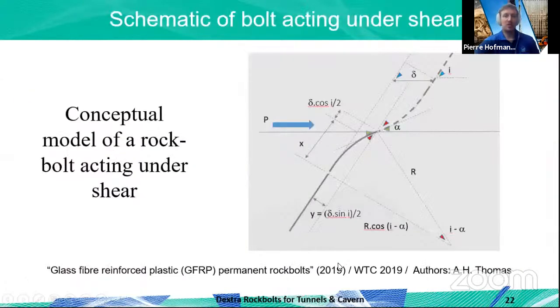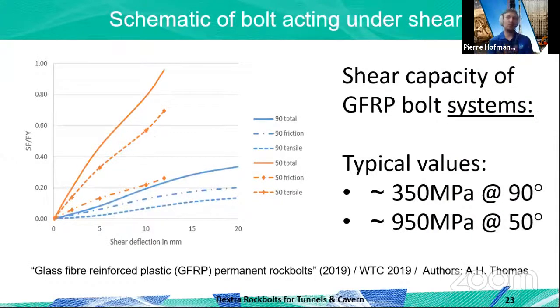And why is that? Because when you allow some deformation, you don't have a pure shear deformation anymore. You have one component in tensile and one component in shear. And because the tensile strength of the GFRP bar is so high, having this split between the tensile and the frictional, you're able to get much more out of it. There are even papers published about that. I just wanted to conclude with that. At 90 degrees, you see that GFRP rebar can develop around 350 MPa. That's according to this study, and that's really not that bad. It's 75% of what the steel bar would develop.